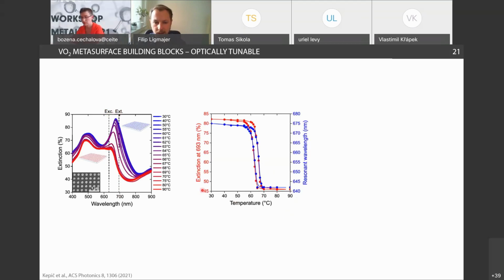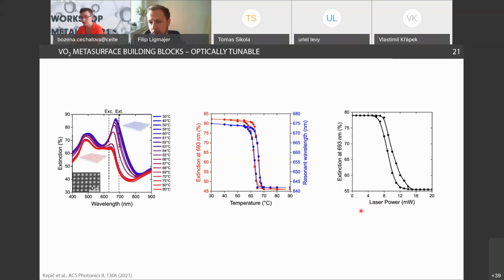Here it is still using external temperature. So this is basically a cross section of extinction at this measured wavelength. So again, here we can see this characteristic hysteresis behavior, but now it is caused by the nanostructured VO2 itself. Also, the resonance, of course, shifts from right to left. And here you can see how by increasing the laser power and exciting our VO2 nanodisks locally by an external laser, we were able to tune its transmission at visible wavelengths, which again I think is a promising feature for future work.